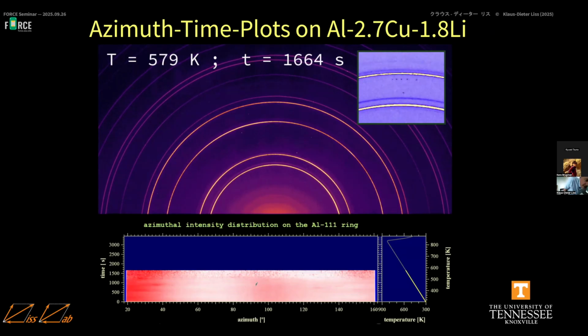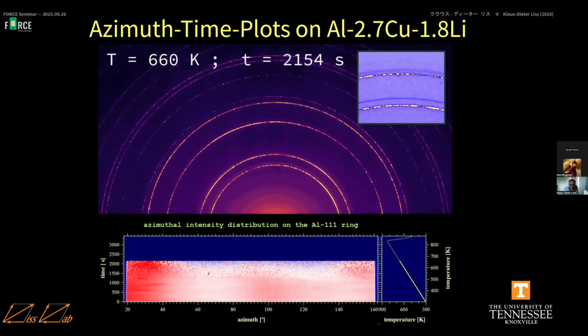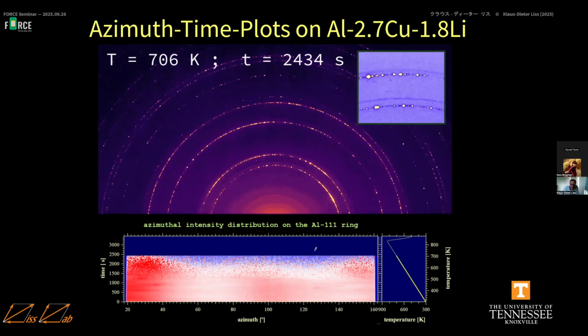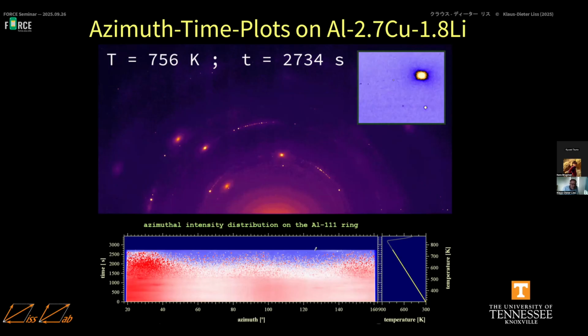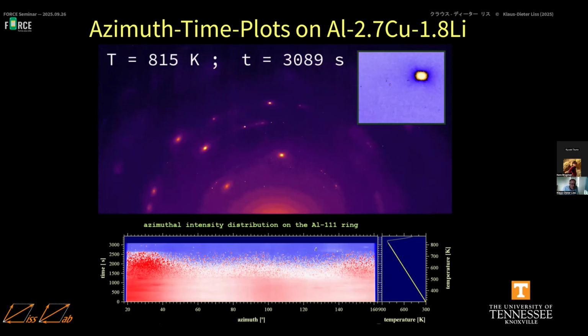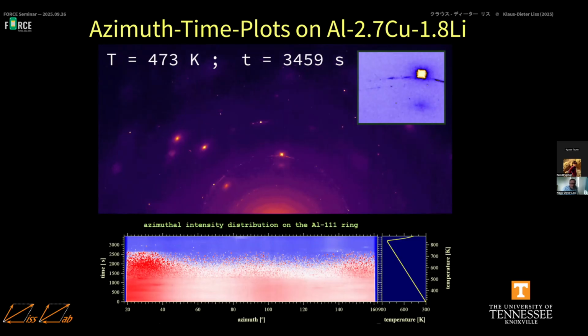And now you see a transition in the morphology of the Debye rings. We have the azimuth here on the bottom, and we see the recrystallization in this regime, and then we see the grain growth. From the number of spots, we can estimate the grain size, because the smaller the grains, the more spots you have on the Debye ring. And for big grains, for a single crystal, most of the time you don't have a spot on the Debye rings. And this is microbeam diffraction.